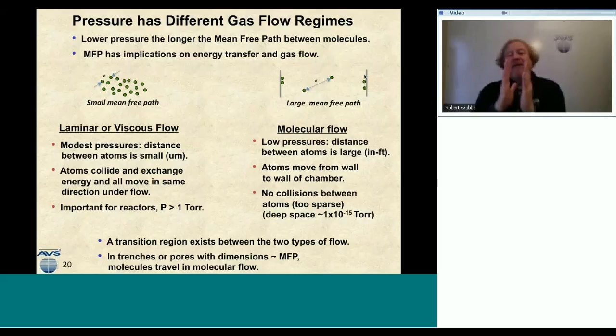And I'm not telling you that you can't coat these high aspect ratios or these very narrow structures. The key is that you have to wait enough time for molecular flow to take place for the ALD molecules to bounce down your trench, and then you have to wait enough time for the products of that ALD reaction to molecular flow and diffuse themselves back out of that trench and out. So the good news is that you can coat these large aspect ratios with very small trench sizes. The bad news is that the penalty you have to pay is the amount of time you have to spend for the ALD process to take place in these trenches.